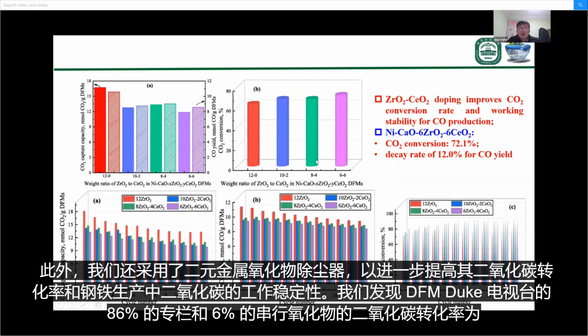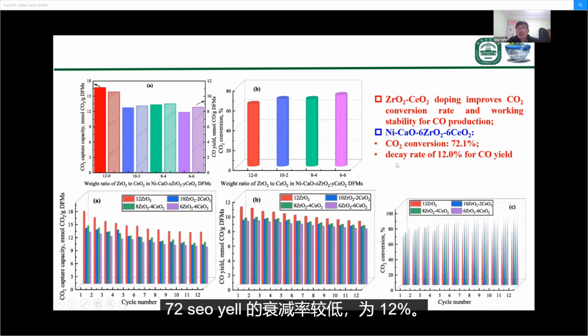Also, we have adopted binary metal oxide doping to further improve its CO2 conversion rate and working stability for CO production. We found that the DFM doped with 6% of zirconium oxide and 6% of cerium oxide possesses a CO2 conversion of 72% and a lower decay rate of 12% for CO yield.